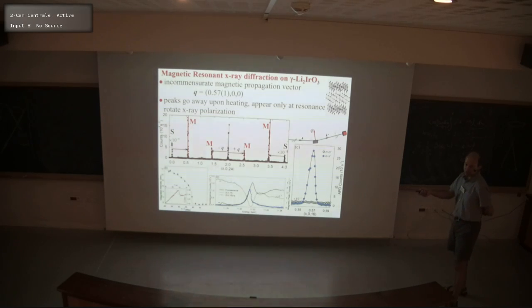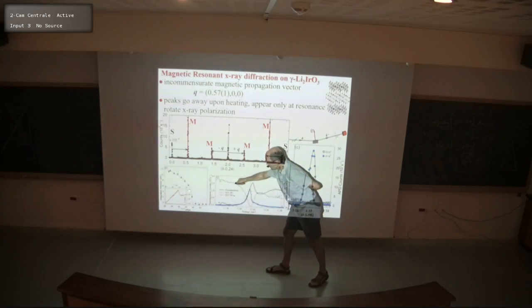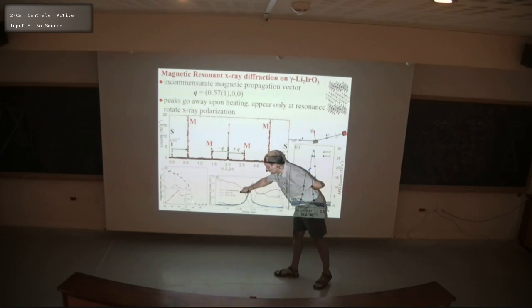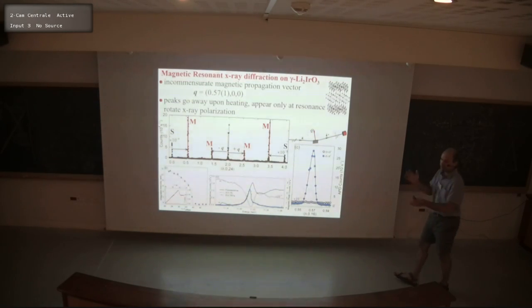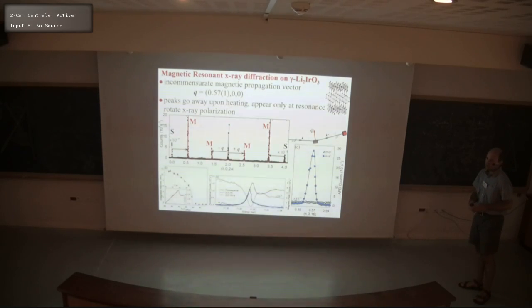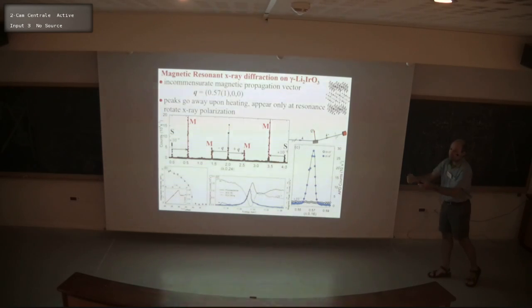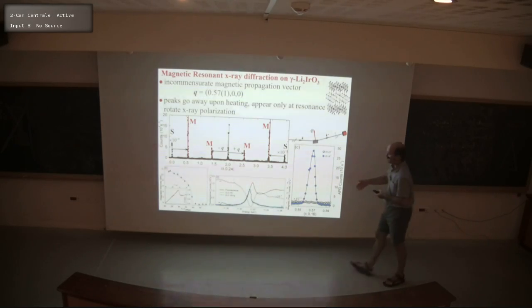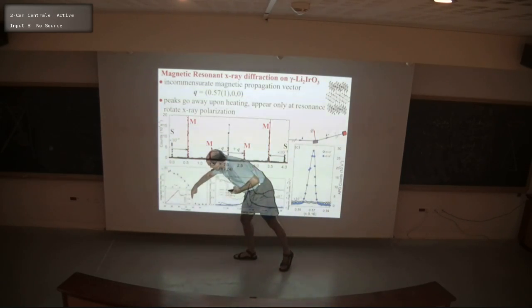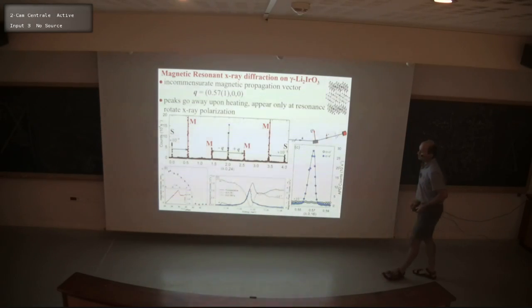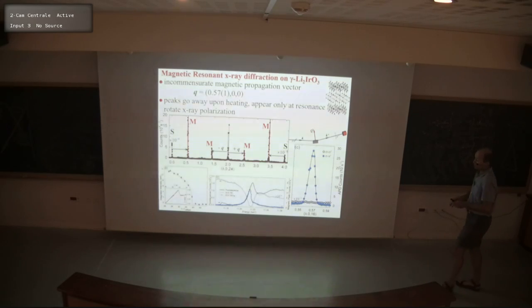So these experiments were done in a CCR, which has a cold finger. So we have a reference temperature where the cold finger of the system is. However, we see there's an offset of a few degrees: if we measure the order parameter, we see that the magnetic peaks disappear at a temperature which is a bit different from the peak in heat capacity. So this temperature offset we can calibrate through thermodynamic measurements that give us a better indication of what the true temperature is. So we always expect that in the experiments we'd see a bit higher temperature because of beam heating. And if we were to reduce the attenuation, this would change. Actually, it would go lower.